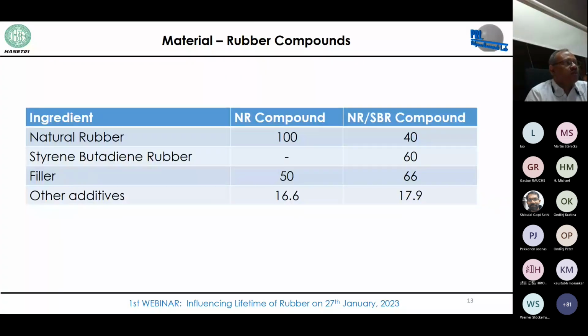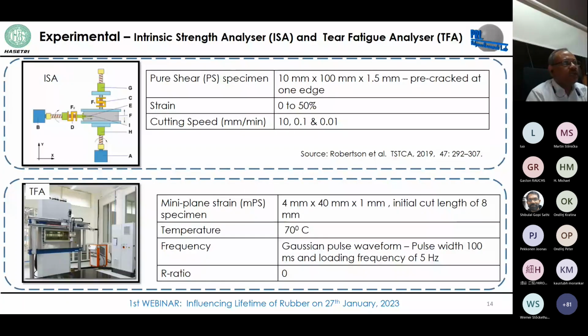So coming to the material, two different rubber compounds were used. One is 100 parts of natural rubber compound. The other is 40 parts of natural rubber and 60 parts of styrene butadiene rubber. The fillers are also all different. It was also shown by Dr. Robertson that filler does not have a very significant role with respect to T0 or the threshold limit.